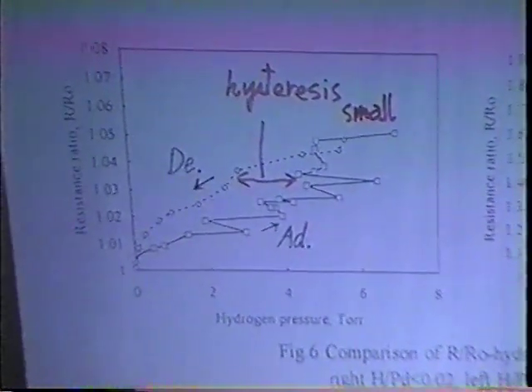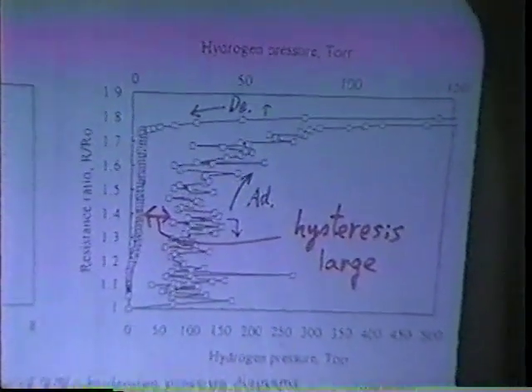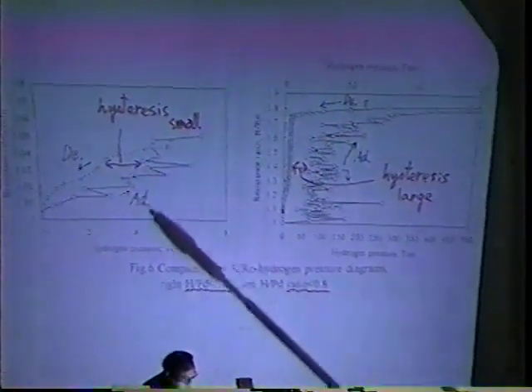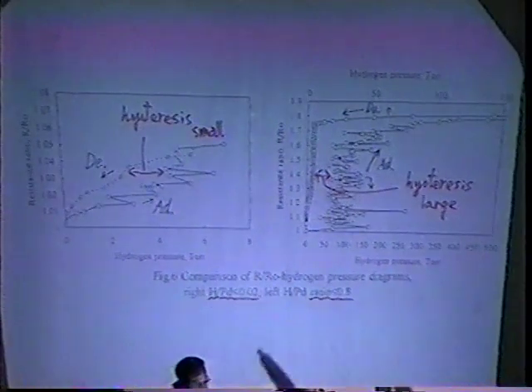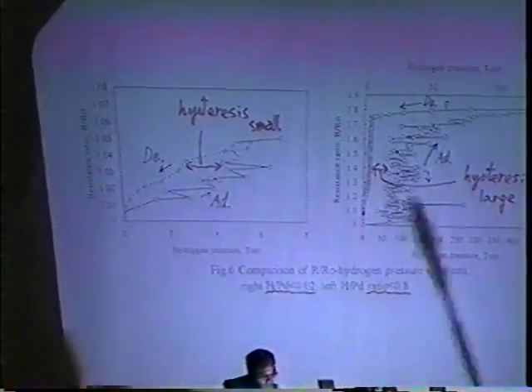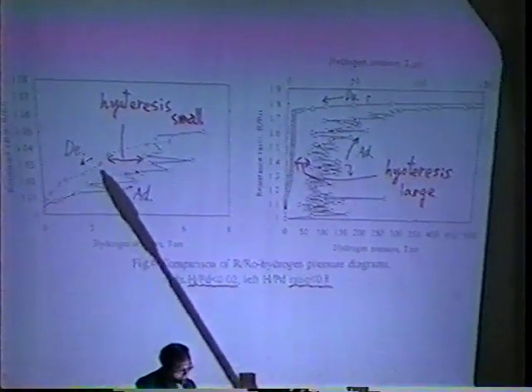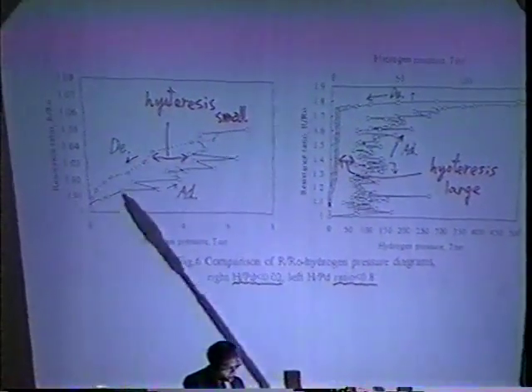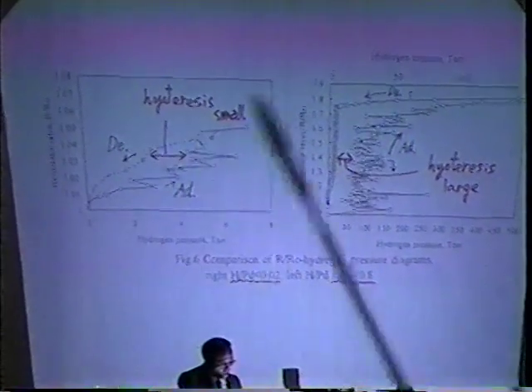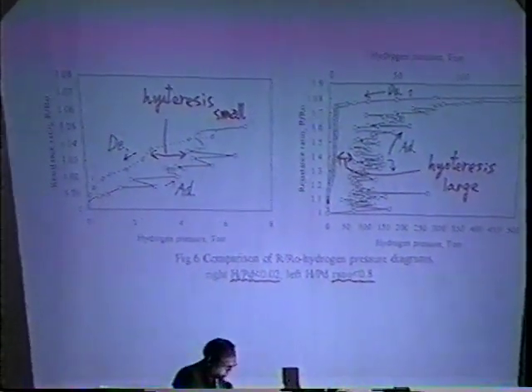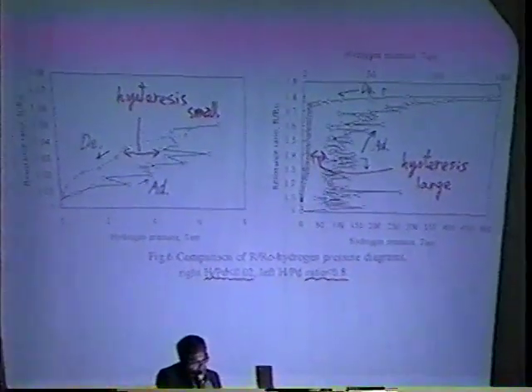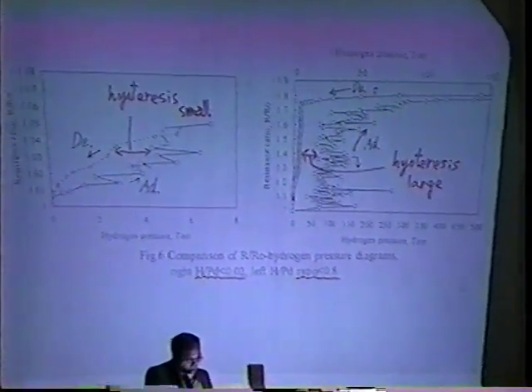I would like to show you one result. This shows the comparison of that diagram, resistance ratio versus hydrogen pressure diagram. The difference is this is a low-level loading ratio, less than 0.02, and this is high level. Hysteresis means this gap, adsorption cycle, desorption cycle. This gap means hysteresis. This is small, and high level loading causes high level of mechanical stress or some defect in the materials. Thank you. Thank you very much.